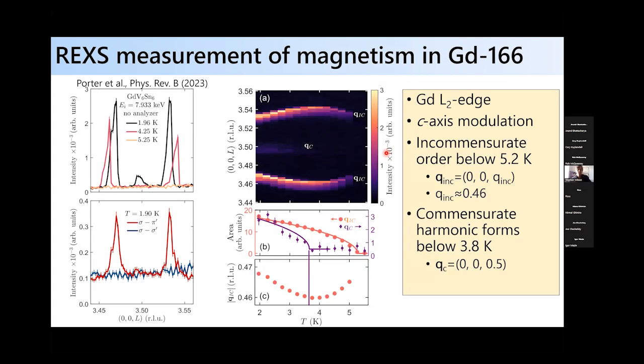And indeed there is. If you do resonant X-ray scattering measurements in this system, tuning to the gadolinium L2 edge, you can cool into the ordered state. This is at 6-ID-B at the Advanced Photon Source. What you can find is that along the c-axis, along the 00L direction here, there are incommensurate magnetic peaks that turn on when you cool below 5.2 Kelvin.